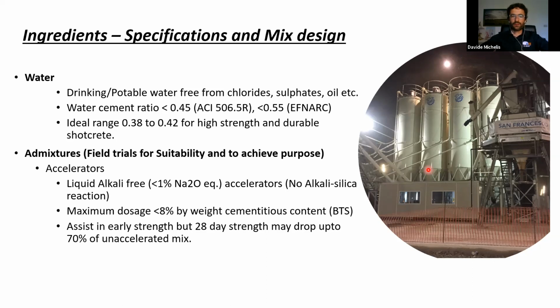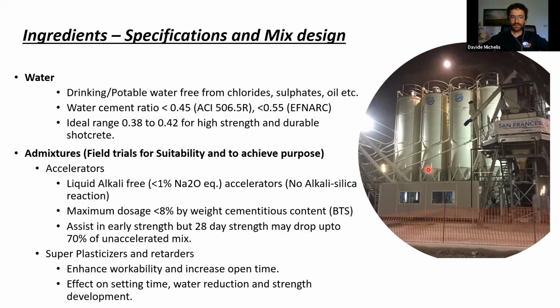To achieve these low water cement ratios, we can use superplasticizers and retarders, which enhance the workability and the open time before the application takes place. And of course, we have to consider which kind of superplasticizer admixture to use, in order to avoid any wrong effect on the setting time of the product.